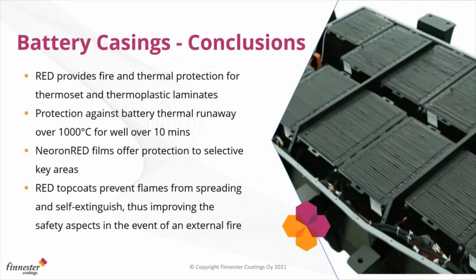So in conclusion, for our battery casings, we can demonstrate that we are providing good fire and thermal protection for both thermosets and thermoplastics. We can protect against thermal runaway, certainly well over 1,000 centigrade, and certainly reaching 10-15 minutes without a problem. The films that Ari introduced earlier would also be useful in battery casings, because that gives you different options in terms of placing those films in certain areas of the casing where the runaway is going to happen, and obviously saving cost and being more precise, optimizing the technology, and also reducing the spread of flame to self-extinguish and preventing the fire from taking hold if there's an external fire from underneath the vehicle.